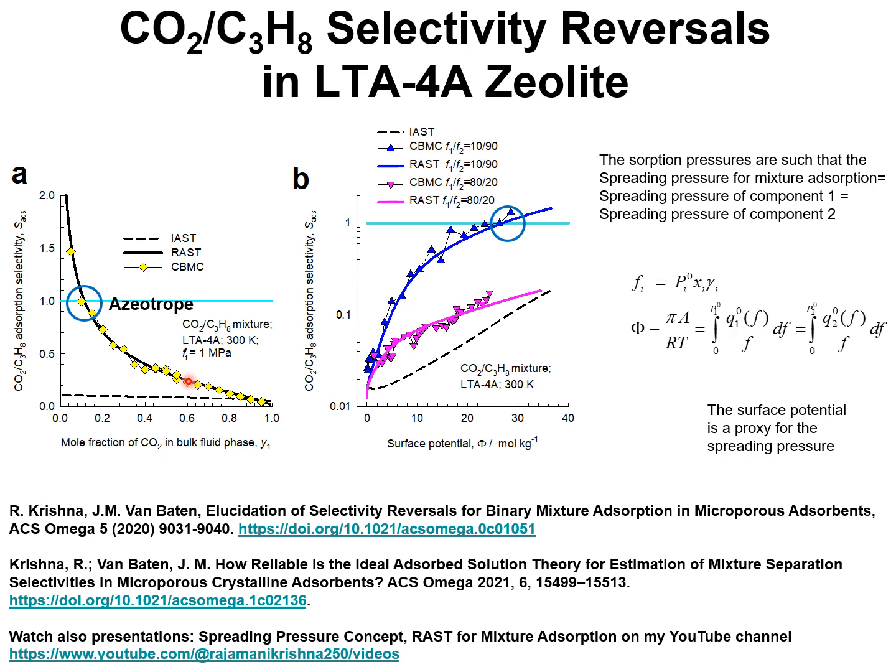Two further molecular simulation campaigns were carried out for 10-90 mixtures of CO2 and propane. The total fugacity was increased from very low values, say 1 Pascal, to about 10 to the 7 Pascals, and the CO2 propane adsorption selectivity determined from the CBMC simulations, CBMC standing for configurational bias Monte Carlo simulation, is plotted as a function of the surface potential.